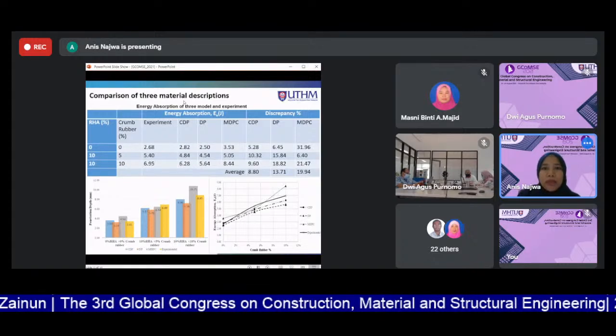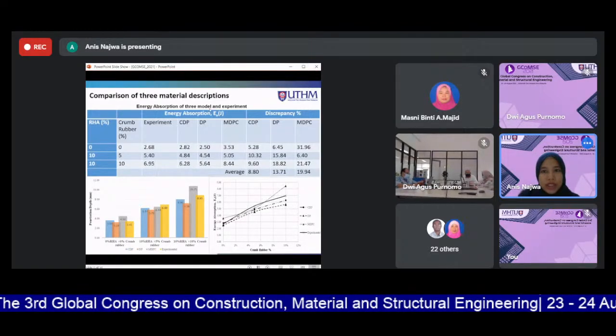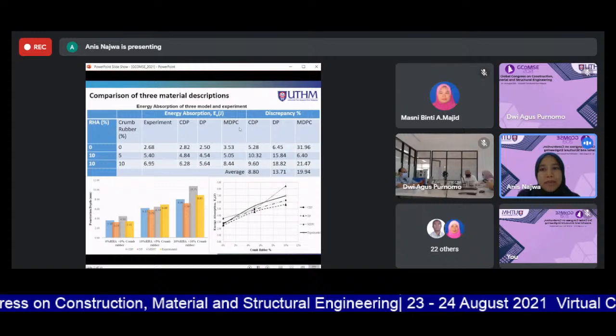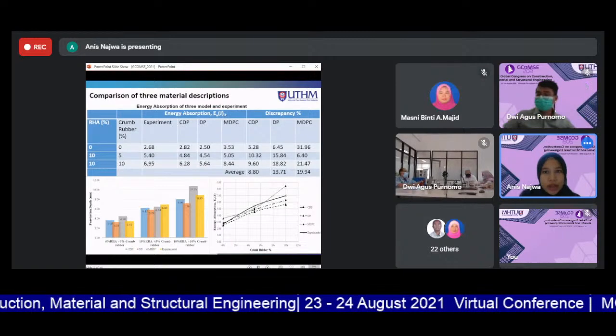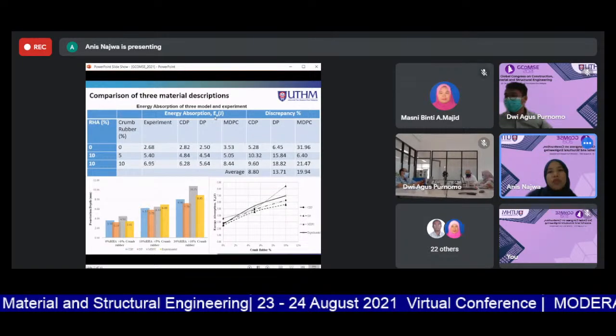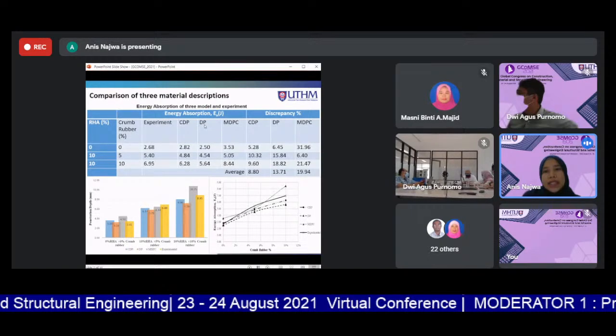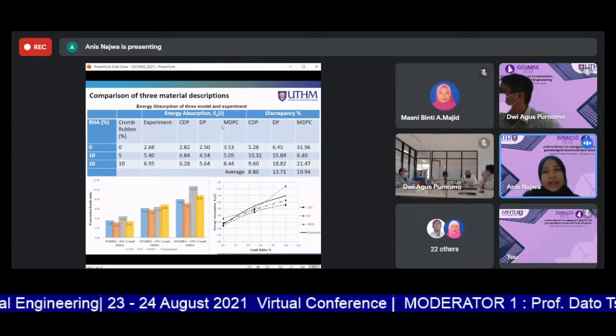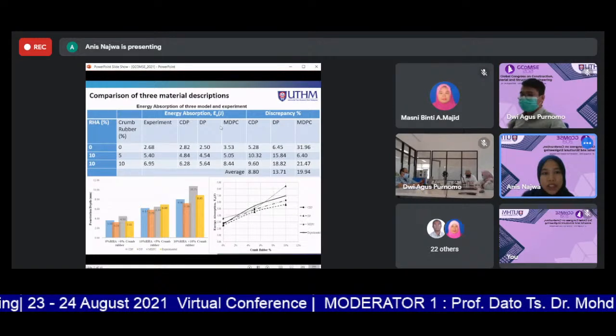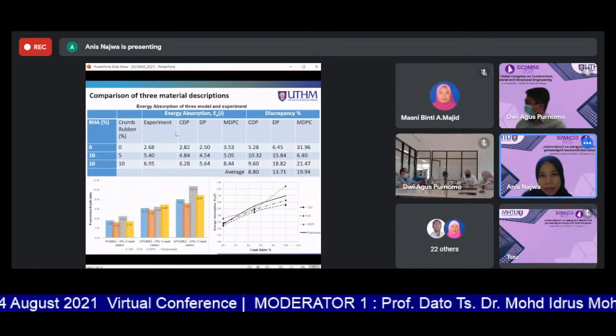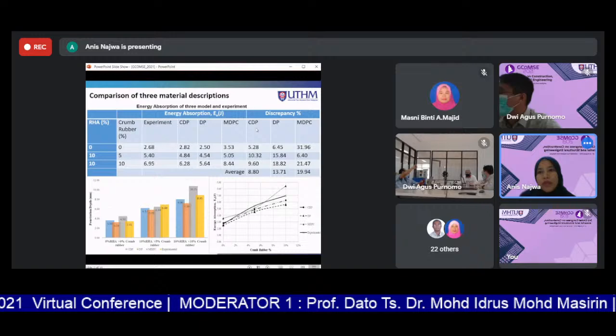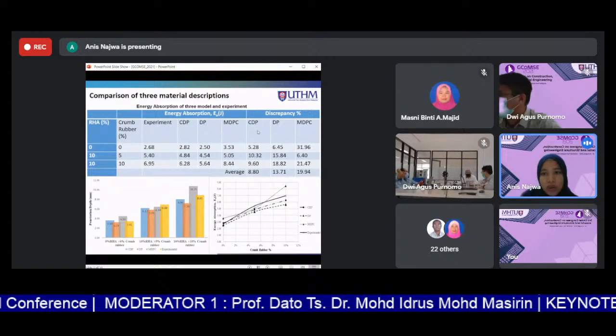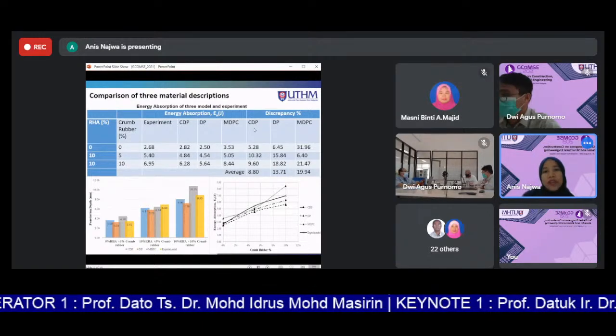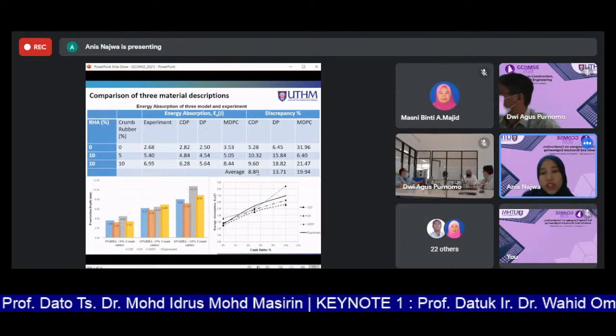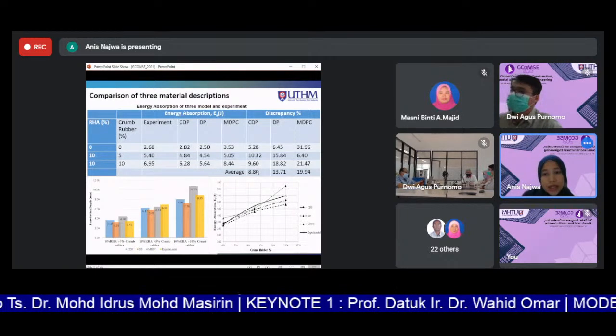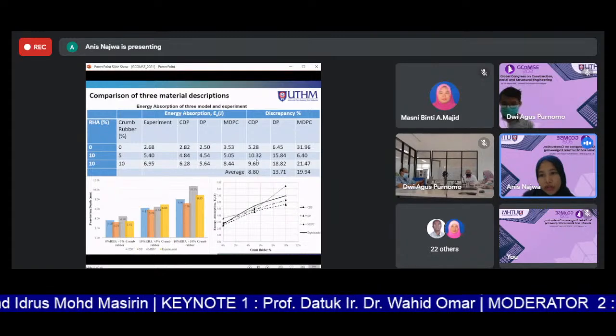So this is the comparison between the three material descriptions, CDP, DP and MDPC, with the experimental work. Here we would like to see which of CDP, DP, or MDPC is nearest to the experimental work. So here we can see that CDP, which is concrete damage plasticity, is much closer to the experimental result, with a percentage difference of only about 8.80.